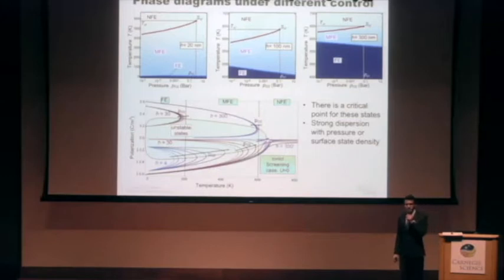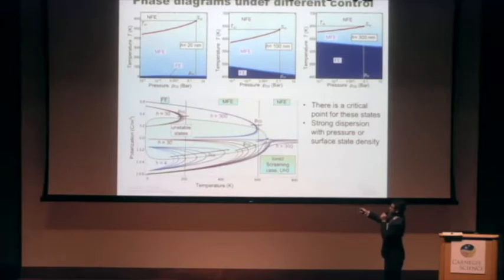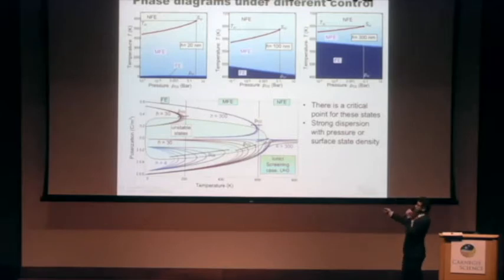You can go ahead and calculate what these phase diagrams should look like. This is an example where Anna has calculated the phase diagram for 20 nanometers, 100 nanometers, and 300 nanometers of barium titanate. You can see this, as a function of temperature and pressure. This MFE is the so-called mixed ferroelectric state. You can see that this mixed ferroelectric state becomes less and less important as you go to thicker films, as you would expect. Interestingly, there are also these kind of strange critical points that exist in these phase diagrams.